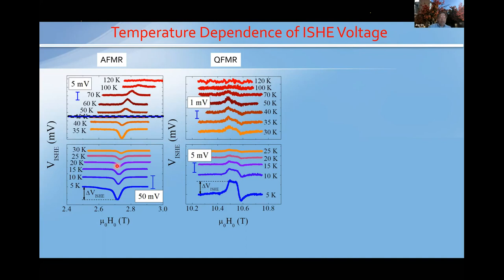So what we can only conclude is there is a handedness switching, right? If you cool down, you have a right hand to left hand switch. So at low temperature it becomes a left-hand dominated contribution here. So what's going on here?